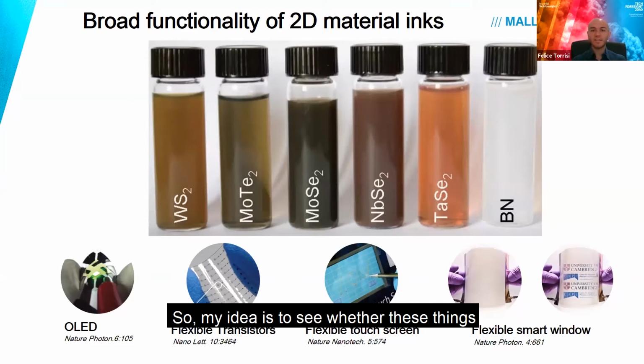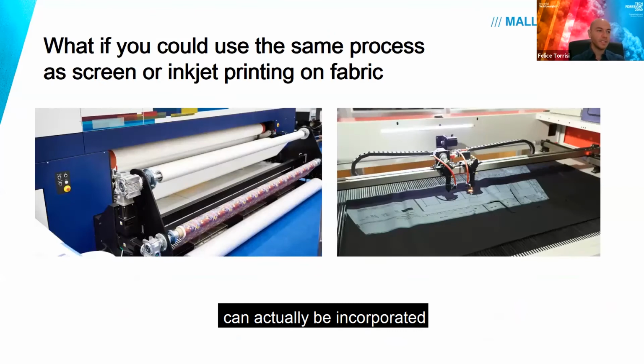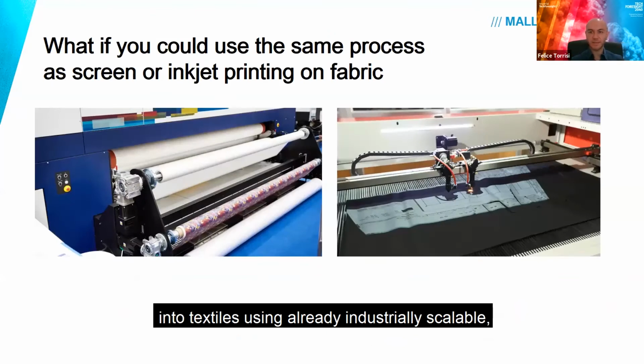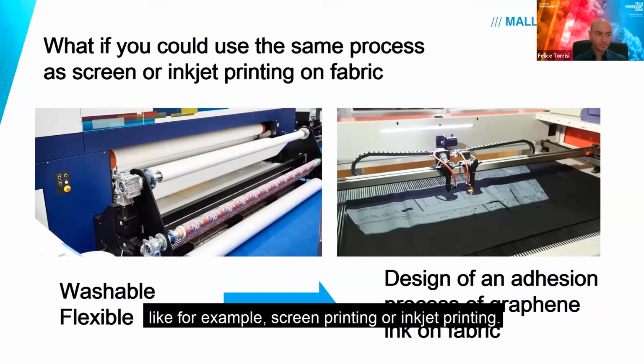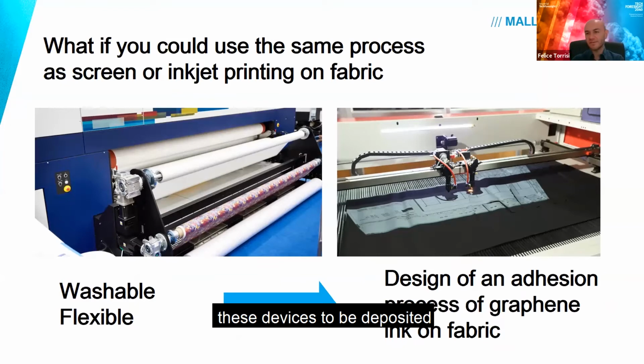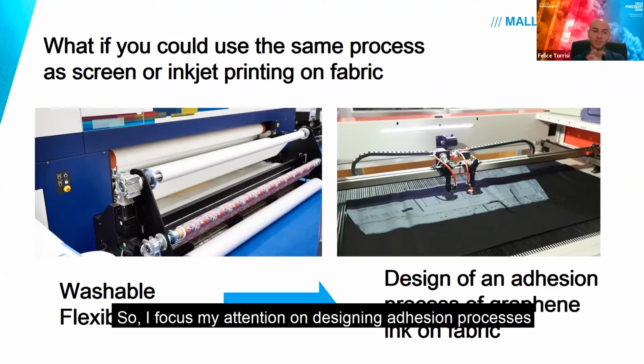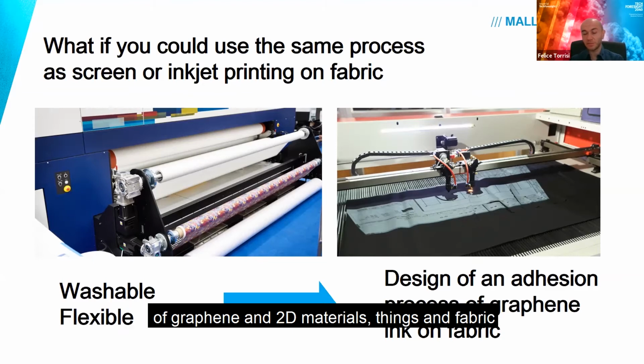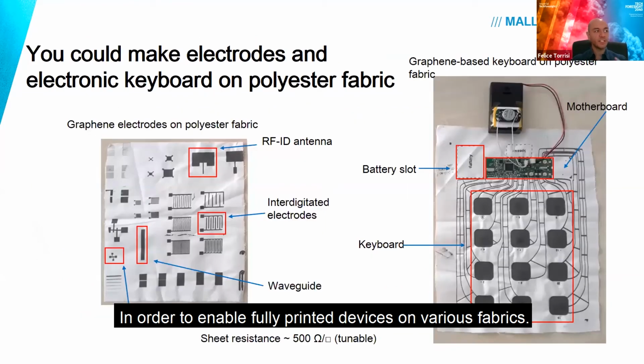So my idea is to see whether these inks can actually be incorporated into textiles using already industrially scalable, industrially relevant printing processes on a fabric, like, for example, screen printing or inkjet printing. And this, of course, requires a technology that enables these devices to be deposited and adhesive to those substrates, to essentially make it washable. So I focus my attention on designing adhesion processes of graphene and 2D materials inks on fabric in order to enable fully printed devices on various fabrics.